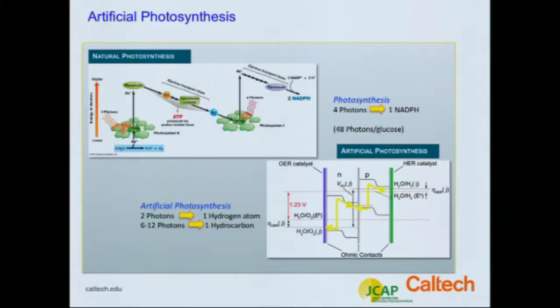To do it at finite current densities, we also have to go a little higher in voltage because of the finite turnover frequencies of the catalyst. When I wear my engineering hat, I like to think of the turnover frequency of the catalyst as effectively a contact resistance—it's due to the finite rate at which you can take charges and turn them into reduced or oxidized species.